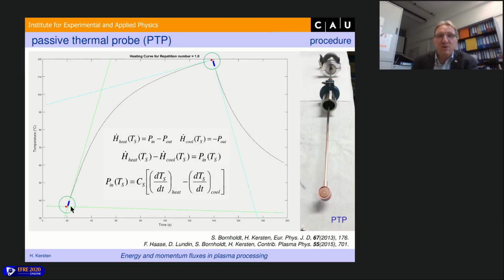You just have to switch on your plasma, and then the temperature increases, and if you switch off the plasma, the temperature decreases. If you cannot switch on and switch off the plasma, then we use a shutter, for instance. So we open our probe and we close our probe, and then we get the same curve, of course. Here you can see this is the probe. This is a kind of a dummy substrate which we insert into the plasma, and we measure the energy flux to this substrate.